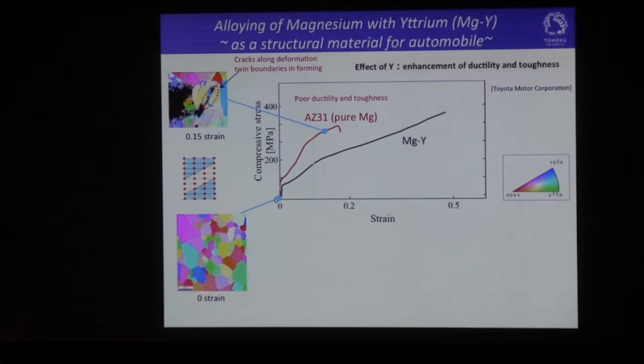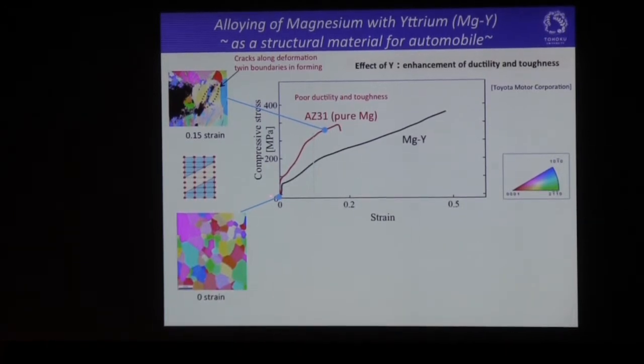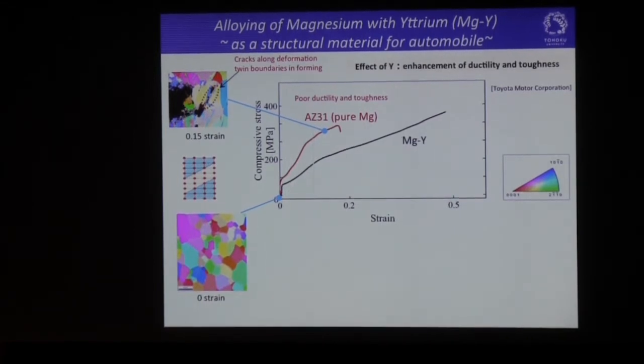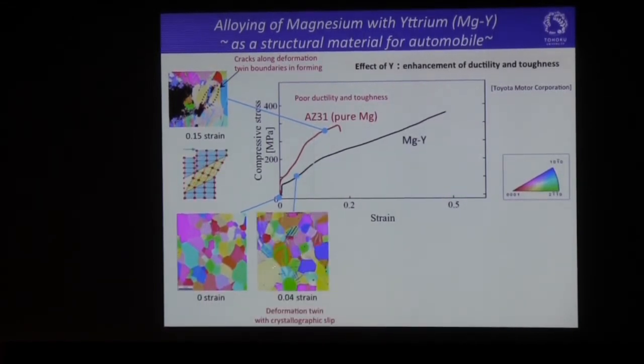Then look at this microstructure. This is the polycrystalline aggregate of the magnesium alloy. Then we apply compressive loading on this microstructure. We have this kind of deformation twinning here with crystallographic slip.